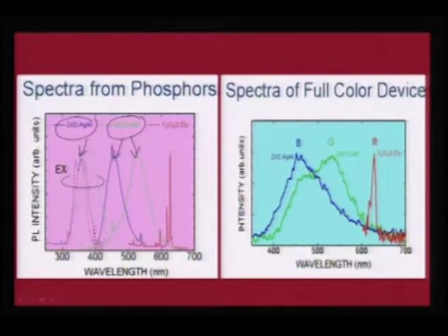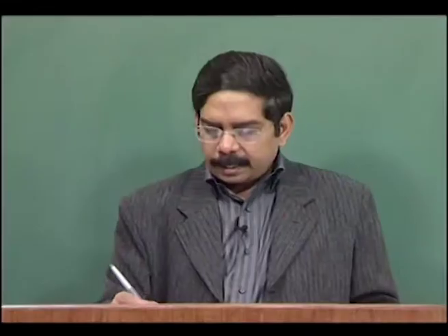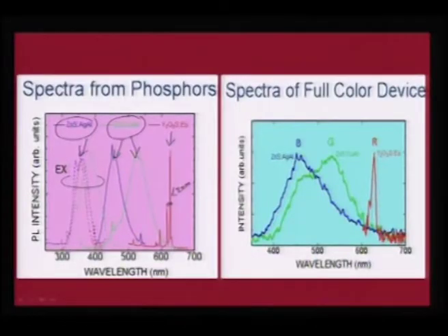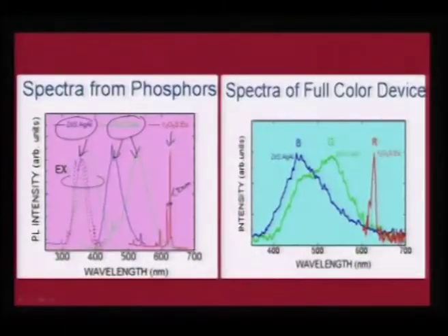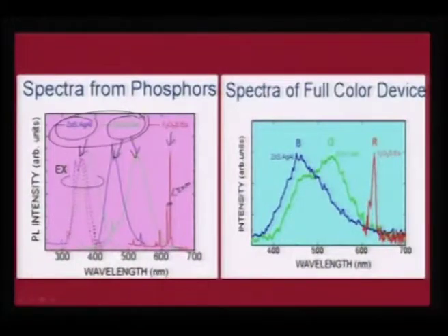So, these two candidates give the blue and green component, and as you see here, yttrium oxysulfide phosphors doped with europium usually give a very strong red light, and if you look at the full width at half maxima, it is only ranging to less than 2 nanometers, which shows how selective this luminescence can be compared to the other two phosphors, and this is mainly because of the mechanism of photoluminescence that is operating in the zinc sulphide based phosphors compared to yttrium based phosphors.